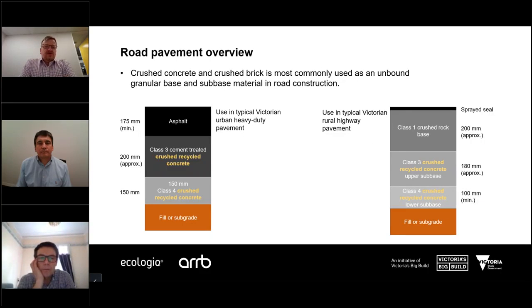I'd like to show you two different types of road pavement. These pretty much represent the extreme ends, I suppose, of the types of pavements that are typically constructed by the Department of Transport in Victoria. And in both of these pavements, there is a role for crushed recycled concrete to be substituted instead of using virgin aggregate. The pavement on the left is a very typical Victorian urban heavy-duty pavement. This is the sort of road that you'd see on a newly constructed freeway, or for that matter, an oldly constructed freeway. Hume, Monash, Eastlink. It's a thick asphalt pavement, typically a minimum of 175 millimetres of asphalt material.